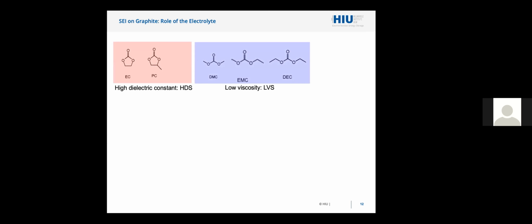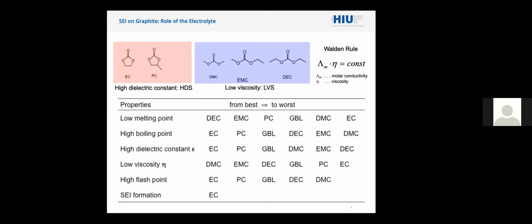Okay, high dielectric constant, low viscosity. Don't forget the Walden rule. In order to optimize conductivity, we need to have high salt concentration, but also low viscosity in the system. Okay, there is no perfect solvent which can do all the job. So if we consider the melting point, we want the battery to work at a very wide temperature range. Then DEC has the lowest melting point, so it's good from this regard. The EC is actually solid at room temperature, so it's not very good.